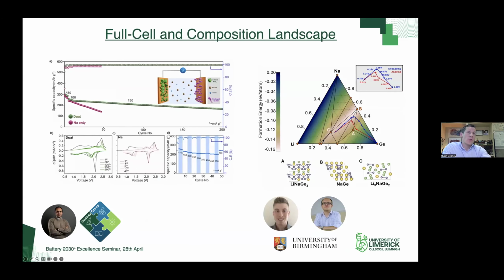So I'll show this here on the right-hand side. This was done through a nice collaboration with the University of Birmingham. And what they helped us with was trying to evaluate this ternary system for germanium, lithium, and sodium. This path that you see here is through the alloying, which is shown in red, and the dealloying path in terms of the composition that we were able to extract from that ICP that you see before.